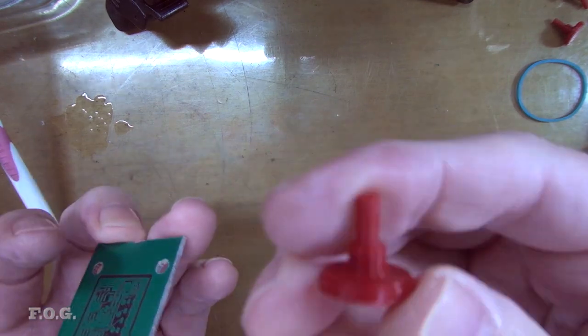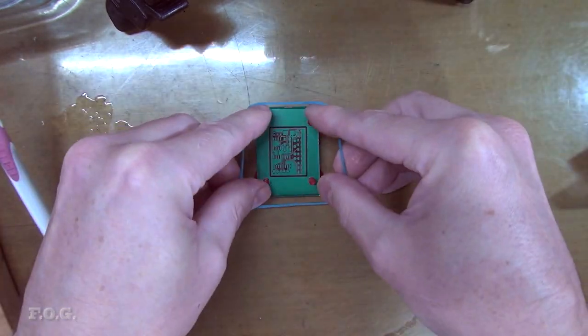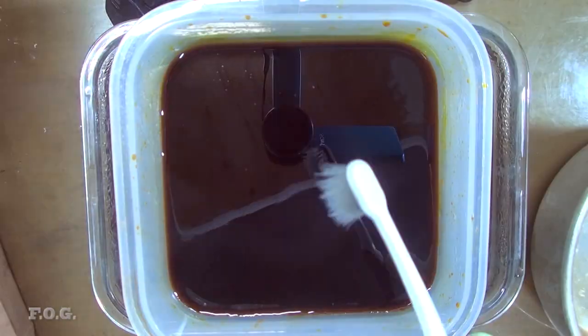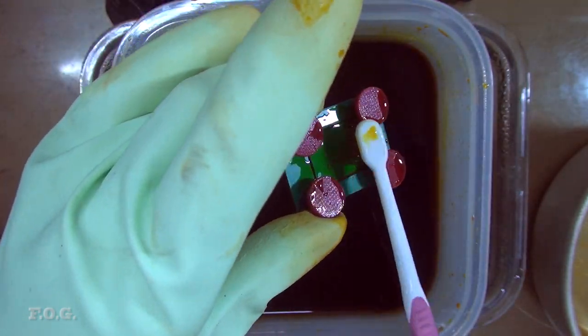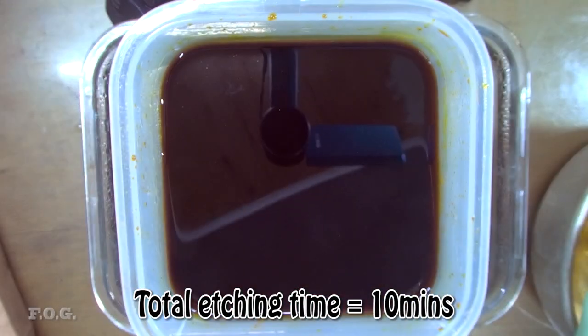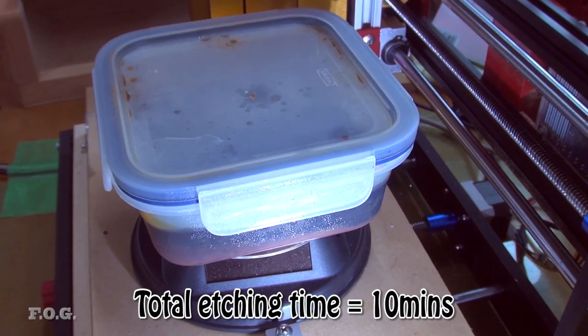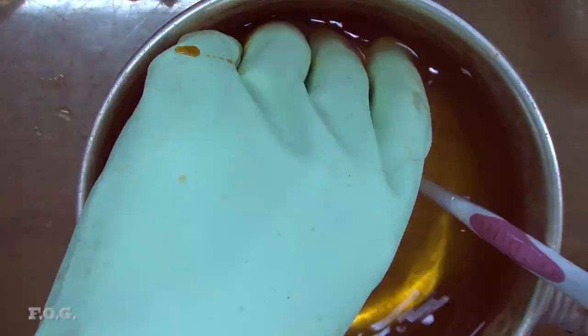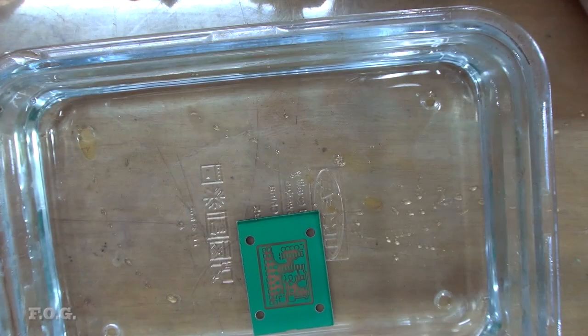I fixed my cute little etching stands. Actually, I made them a little bit too small, so I'm using a rubber band to stop them from falling out. I like to warm up the etchant in a boiling water bath. This seems to speed up the chemical reaction quite a lot. I also scrub the etchant into all of the traces with a fine toothbrush. And as you likely saw in episode 5, I now use the CNC in combination with the UV exposures rotary base to get a good agitation. Pop all the stands off during the first stage water wash, and then do a final wash in some clean water. And the result looks really great on both sides.